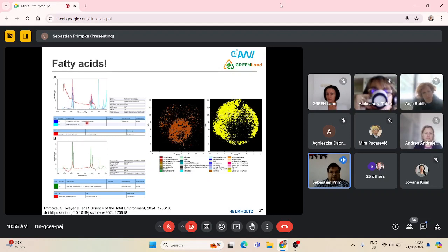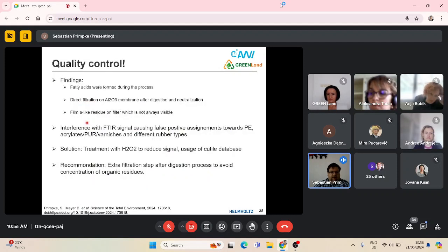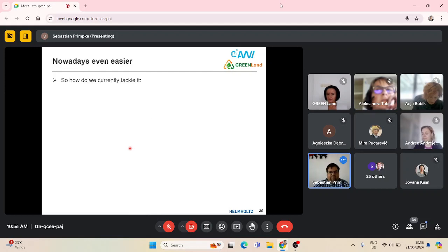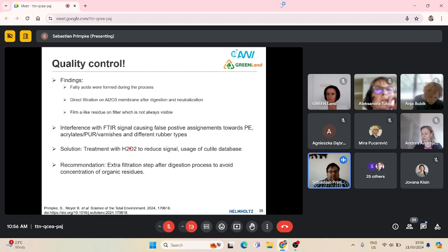So we did another chemical treatment and also used a different digestion process. We added hydrogen peroxide afterwards and used the cuticle database, and then we were able to successfully analyze the samples. But the numbers reduced from 5 to 90 microplastic particles per individual sample to 4 microplastics in total in all of the investigated species. And this has a rather high impact.